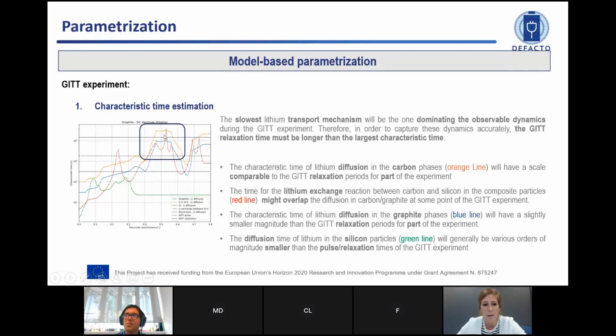First, we have the orange line, which is related to the diffusion in the carbon phase. What we see is larger than the relaxation time, so this means that this one is dominating, and we will see it in the GITT. Then we have the red line, which is this one. Again, we have a certain peak at a certain SOC, and in this case, it's something that we also observe in the GITT, and it's dominating again.